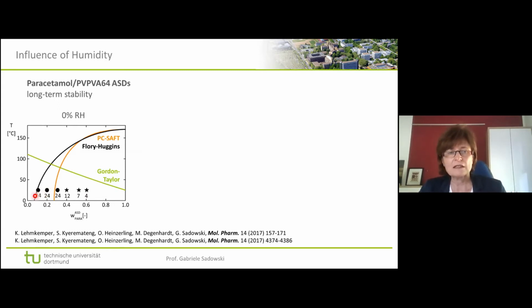And what you see indeed is that after 24 months, so the numbers here indicate months, we did not find crystals left of the solubility line. So that means this is what we expected, and this is ongoing. From time to time, we take these samples out and see whether we find crystals, yes or no. And so far, we did not find any sample which violated our predictions.